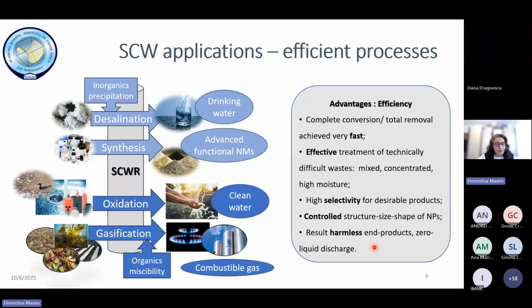Based on its solvent properties, under supercritical water conditions the inorganics are precipitated and the organics are highly miscible with water. Supercritical water finds some efficient applications. We can obtain clean water by desalination and oxidation. We can obtain functional nanomaterials by synthesis under supercritical water conditions. And also by gasification of biomass, we can obtain hydrogen or methane, so combustible gas.